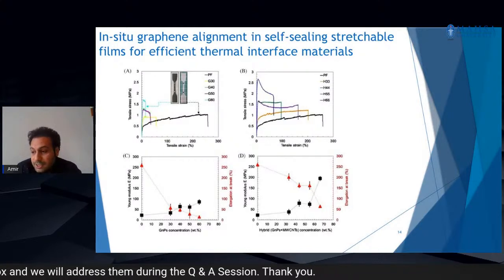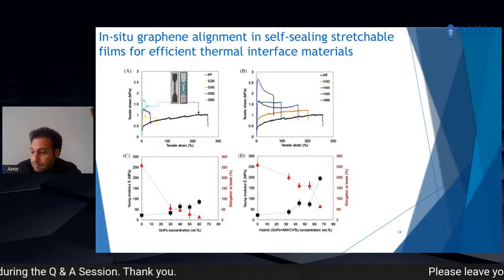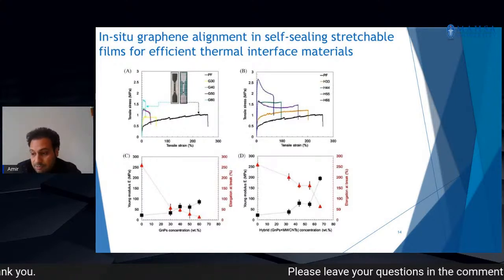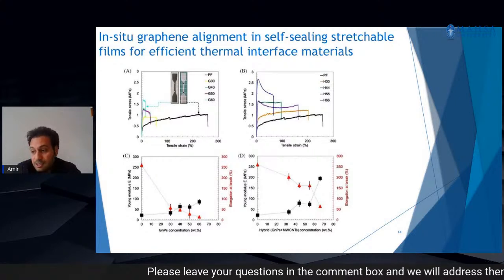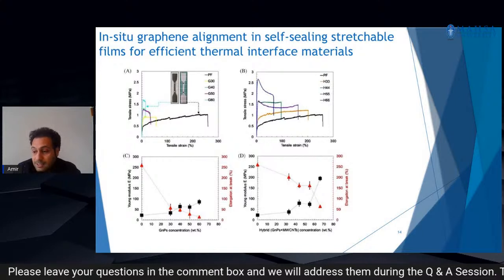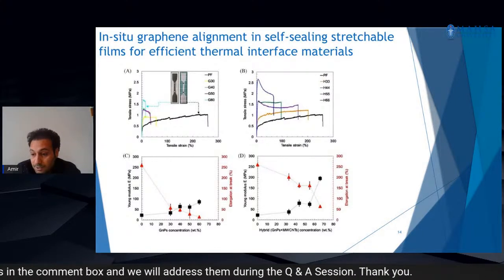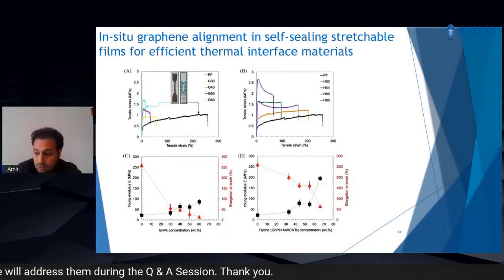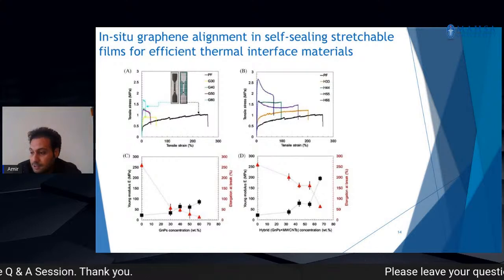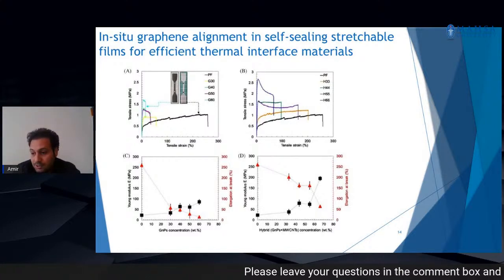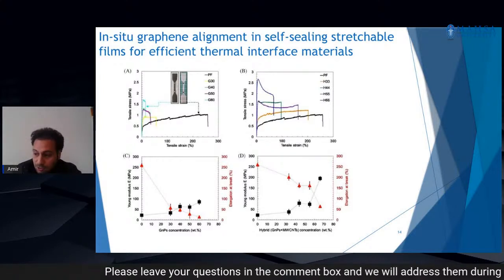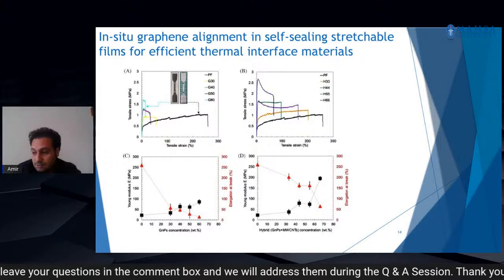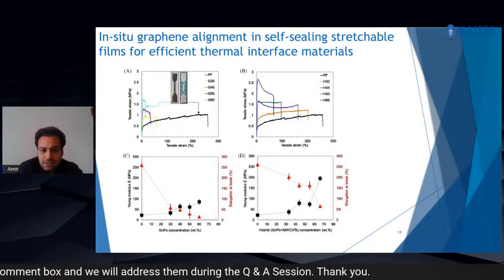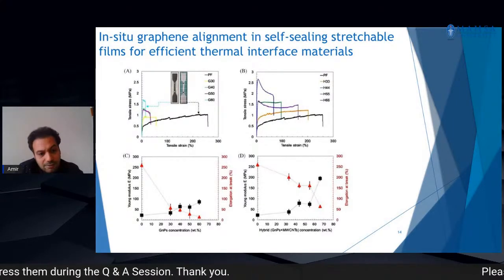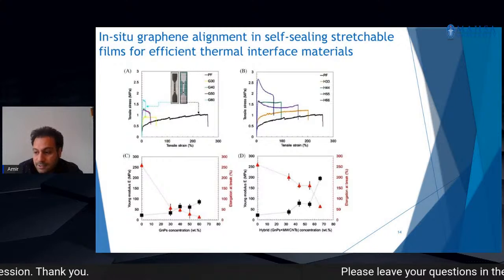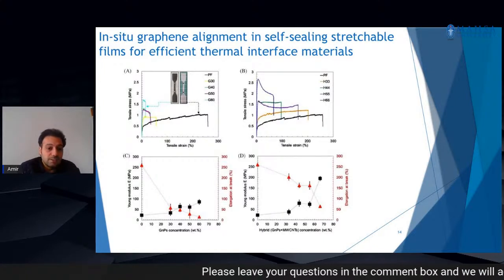So by using the compression molding hydraulic hot press that we use, we fabricated a graphene-based thermal nanocomposite pad with high thermal conductivity using a self-sealing stretchable film known as Parafilm. The hybrid pads were also fabricated with multi-wall carbon nanotubes, MWCNTs, at different concentrations, corresponding to 10% and 60%, 63%. We showed a significant enhancement in the thermal conductivities we measured.